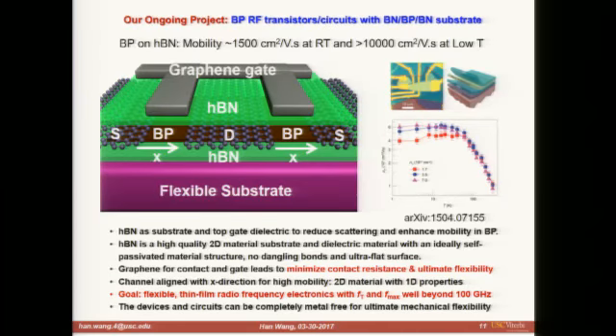In our ongoing work, we have been working on a boron nitride, black phosphorus, boron nitride sandwich device structure, in which we measured mobility above 1500 at room temperature and over 10,000 at low temperature. We're aggressively scaling down the channel length of the transistor, and we hope to push both FT and Fmax above 100 gigahertz in this device structure, because boron nitride can provide very good encapsulation to preserve the high electronic integrity of the BP material.